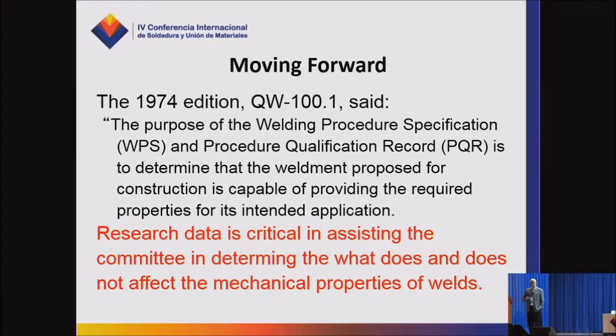So if you have a sound weld and you make the weld in a flat position, in a vertical position, in a horizontal position, in overhead, does that change the properties of the weld such that you can measure a difference consistently and uniformly? No. If you have a sound weld, the weld doesn't know and doesn't care what position it was welded in, right? Unless you're welding unobtainium. If you're welding unobtainium, it knows and it cares. But unobtainium's not in the code, and good luck with getting unobtainium.